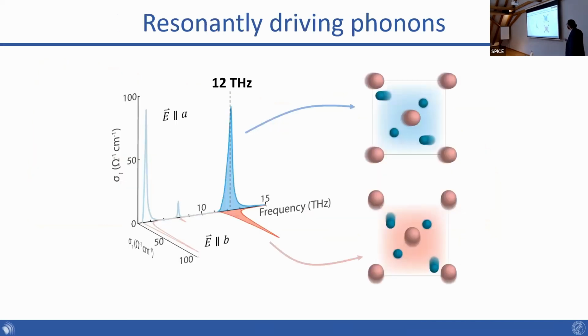In order to do this excitation, we need to figure out which modes we can pump. Here's the optical phonon spectrum of cobalt fluoride along the two axes. You have these three possible modes you can choose from. They're all three EU modes. You can then use DFT to calculate which ones will have the strongest coupling to this Q_R mode that we're interested in. And it's this one at 12 terahertz.